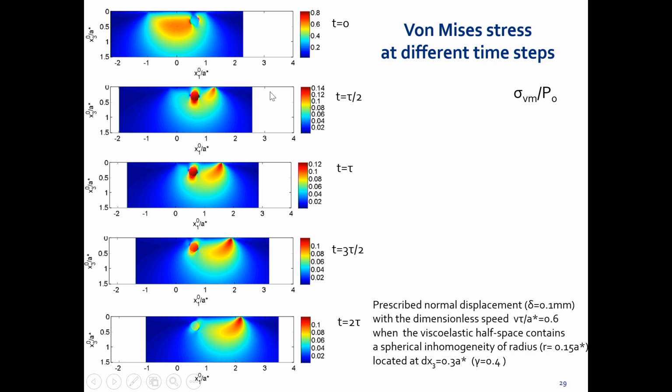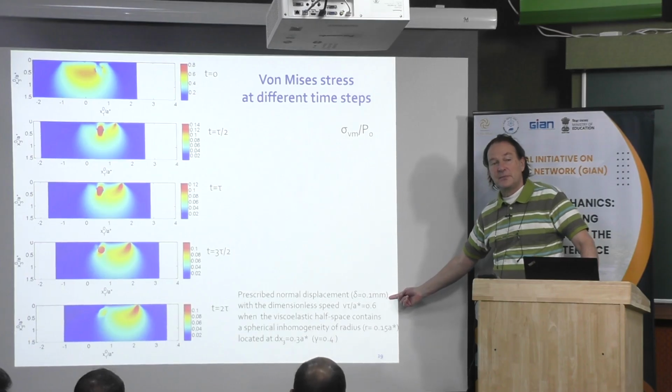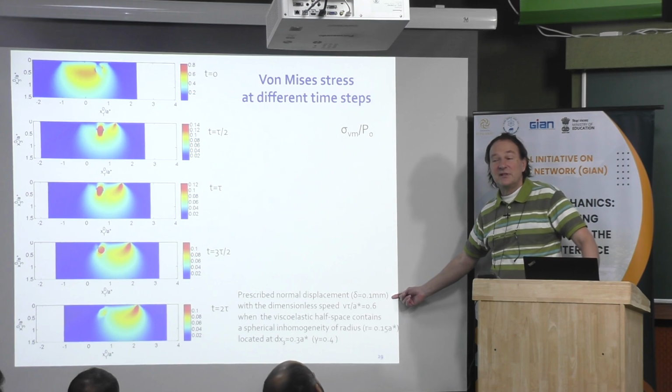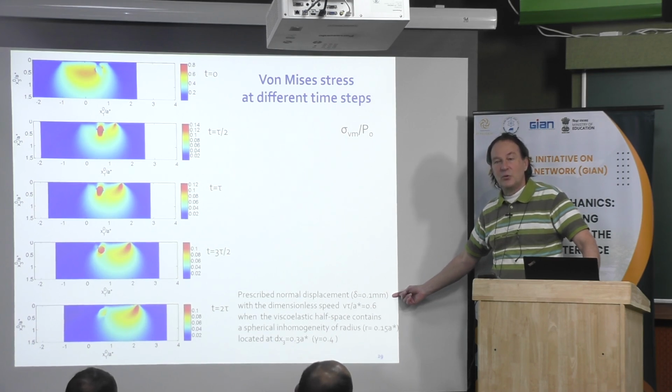However, here we apply displacement. Then when we apply a displacement, in fact, the load is decreasing with time. Then for those that are working on polymeric materials, for example, if you are working on bearings made on polymers, you have to be careful when you apply the load, if it is a load or displacement.